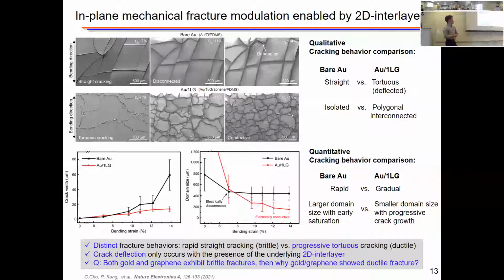A little bit of quantitative analysis. With the fracture domain size, we saw early saturation of the fracture domain size in the case of gold without graphene, whereas we observe a continuous, progressive reduction in the domain size in the case of gold with graphene. This early saturation of fracture domain size indicates that there is no strain energy dissipating through the cracking. The excessive strain energy goes into interfacial fracture that may cause debonding failure. Another interesting observation was that the metal 2D, or gold graphene, electrode maintained its electrical conductance at strains above where the conventional metal electrode shows complete disconnection.